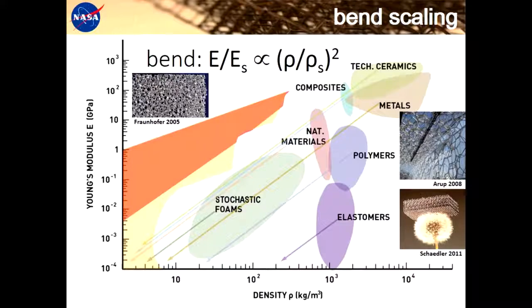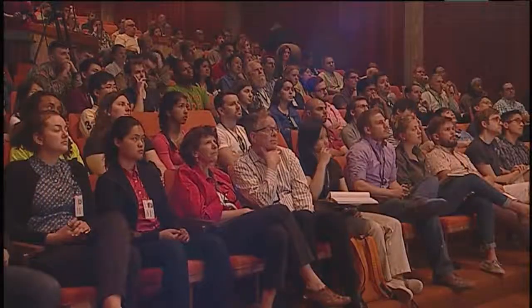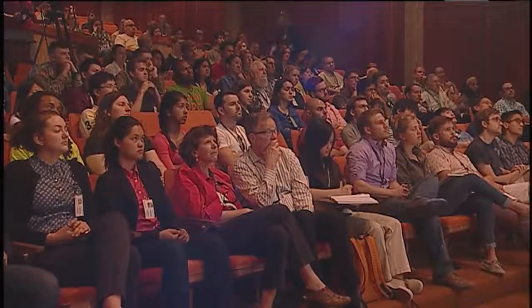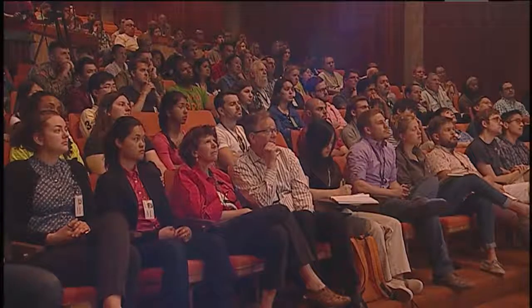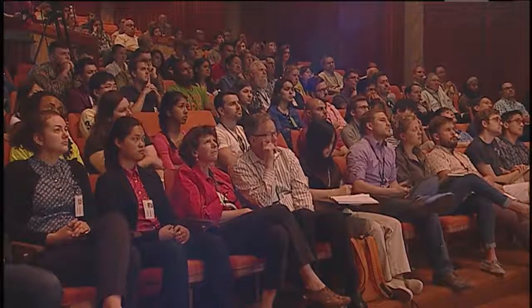And many of these materials can be produced very efficiently, for instance, by bubbling or mixing a liquid state with air before hardening. So it is these kinds of materials that have achieved ultralight status at the extreme left-hand side of this chart. But this still leaves this entire red region of the chart behind due to the effect of the beam bending dominated behavior and the order of magnitude practical limit for the processes that produce materials with proportional scaling. So it's this region of material property space that we've focused on with some success.